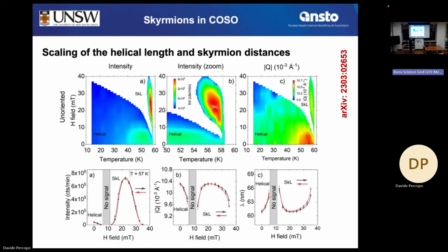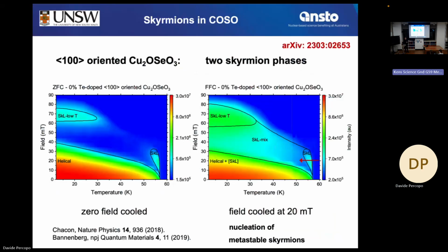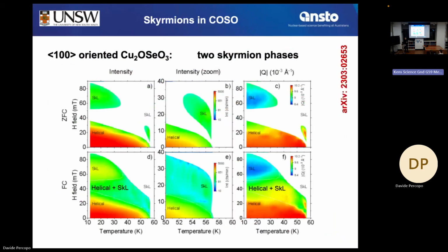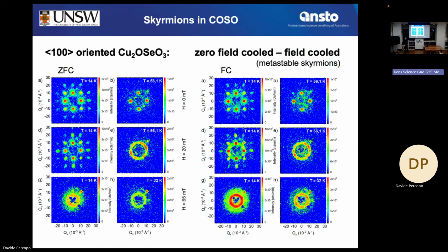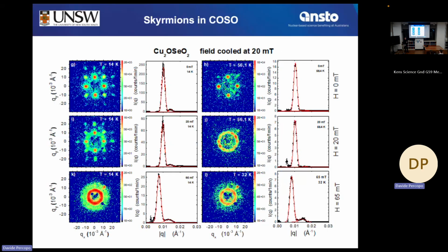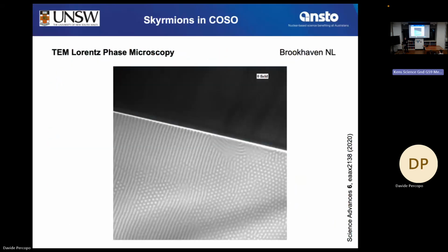So from the Bragg peaks, we also extracted their distances, which is either the length of a spin helix or the distance between the skyrmions in that lattice. That's what we have done here. In our case, about 63 nanometers. And we figured out that they actually expand and even converge to infinity before they evaporate and disappear. That's our core result here. So yeah, we did a couple of runs. I skipped that. This is actually the raw data and how we analyzed it. But I wanted to show you that one.